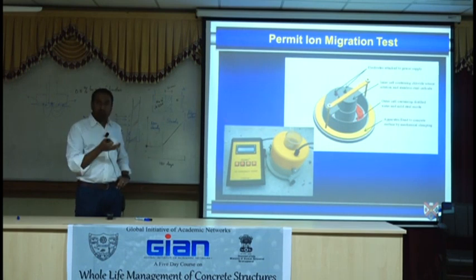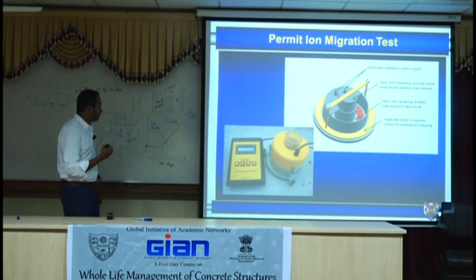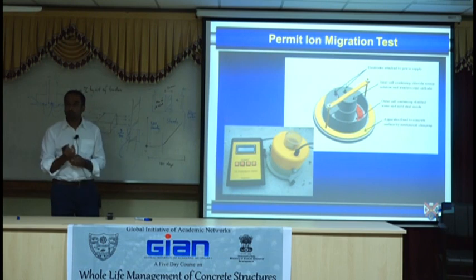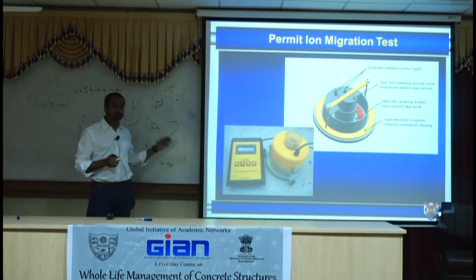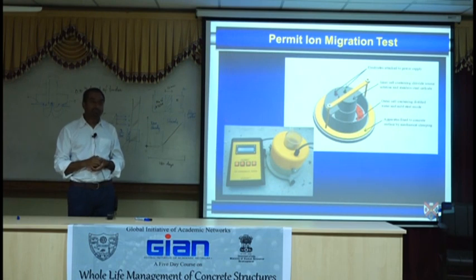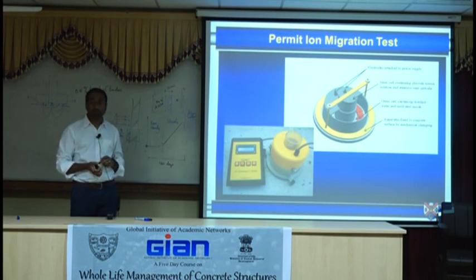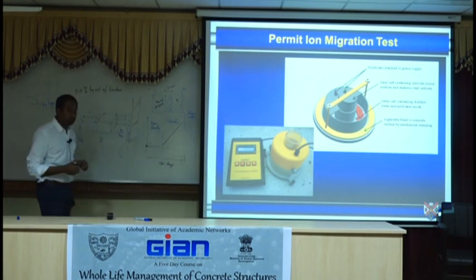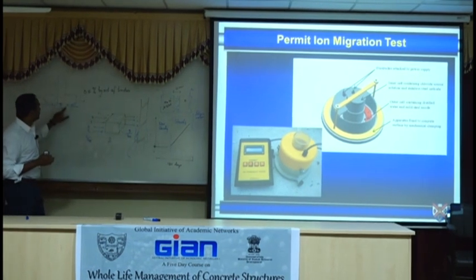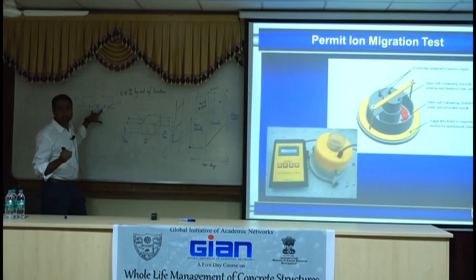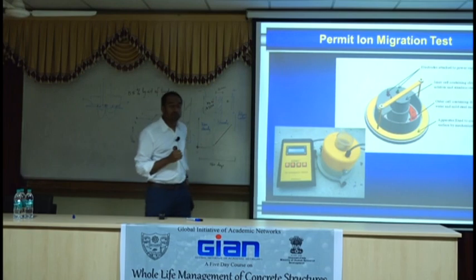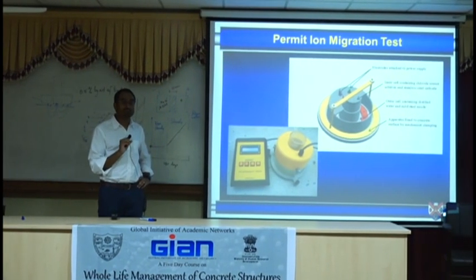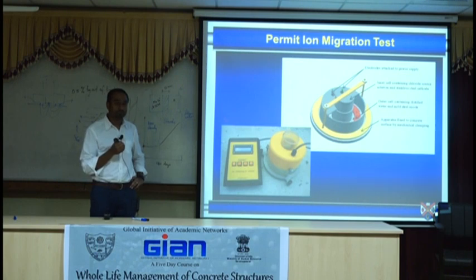You can ask whether we did work on different other ions. We did, but all of them fail to give you very close results. We know we can use nitrates, it'll do the same sort of behavior, but it takes days to get a result. A test can finish within 24 hours, 6 hours most of the time, 24 if you're using extremely good quality concrete. If you're using super high performance concrete, the flow will be limited to the surface, very much surface. You're talking about 5 millimeter if you're lucky. That's because that concrete is extremely dense. You shouldn't have to test them. Okay?